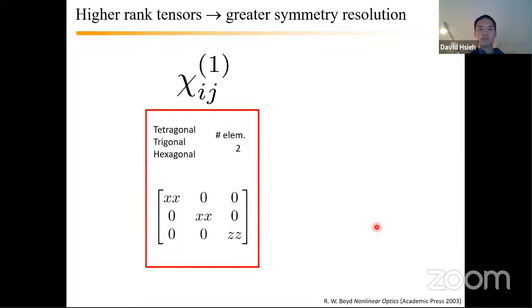The downside of lower rank tensors is that there's often a lot of degeneracy between different crystal classes. So, for example, if you were to look at this linear chi 1 response in different crystal classes, like these three, for example, there are really only two independent elements, XX and ZZ, and they all look the same, despite the fact that you're in different crystal classes. And that impedes the ability to perform careful refinement between crystal families.